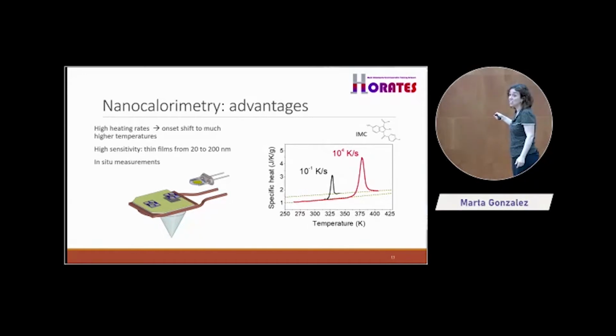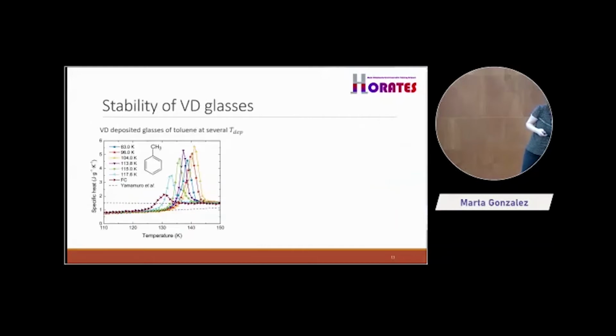Our transition is shifted to higher temperatures with these nanocalorimeters, because we're going so fast that we don't give the sample time to go to equilibrium until a very high temperature, okay? So this gives the advantage that we are able to explore a temperature region that is not accessible with conventional techniques. So now you know the technique.